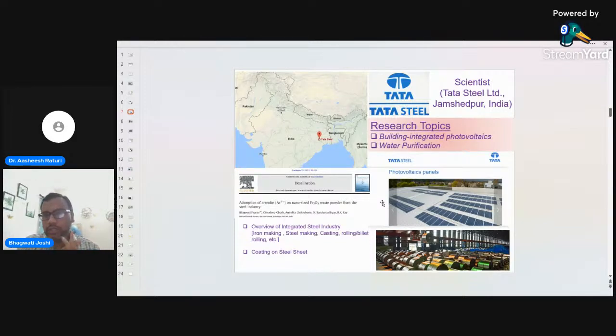What we have done, which is pretty novel, is that we use the steel industry's waste oxide fines. In the steel industry, they produce oxide fines when they make steel sheet. During steel making, the molten liquid iron forms a thick solid slab, the hot slab. Those hot slabs are cooled down with water, and then using the cold rolling mill, they roll this thick steel into thin steel, which is converted into sheet